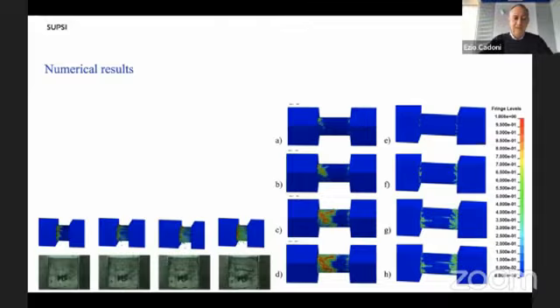The entire system was modeled by using LS-DYNA, explicit solver with hexahedral elements, and the experiments were simulated by integrating the constitutive equation of our model with the boundary condition setup of the UHPC and the fiber reinforced material. This slide depicts the damage evolution of the two materials, where the color indicates 1 for fully damaged and 0 for intact material. And this shows the good suitability of the DAMP model in reproducing our test.